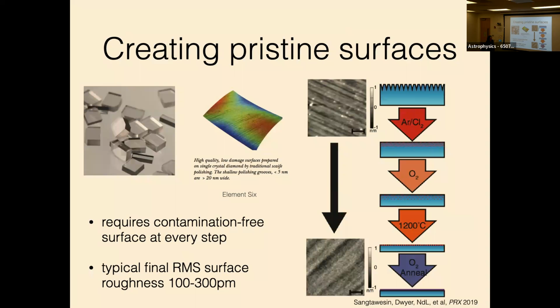And then the key thing is that you have to do this in a way that you don't introduce these surface morphology problems. So you have to really do contamination-free processing at every single step. And we're now able to get these oxygen-terminated surfaces with RMS roughnesses of below 100 picometers over a micron, and then something like 300 picometers over 5 microns.